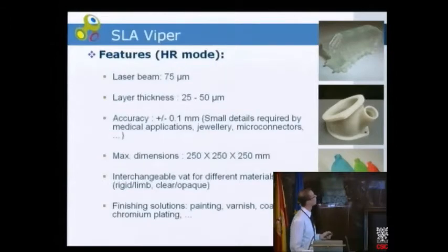Here are the features of the Viper stereolithography in high resolution mode. We have a laser beam thickness of 75 microns. The thickness of the layers is in the range of 25 to 50 microns, and these features can reach an accuracy of approximately 0.1 millimeters for small details required by some medical or electronic applications. And the maximum size of the part we can build with this technology is a cube of 250 millimeters side.